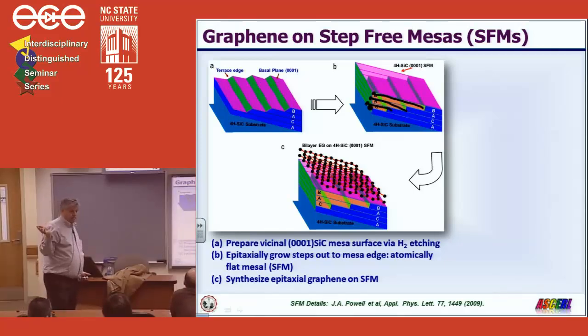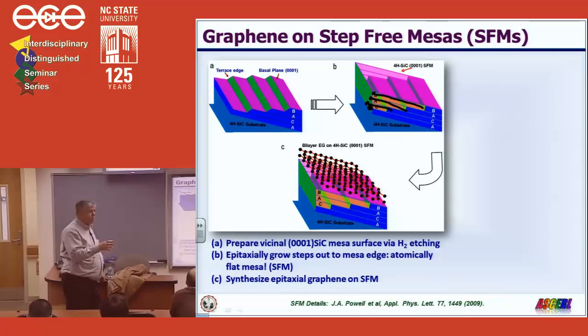I can never grow it out. So you can't just get a 2D nucleation process on the top layer of that mesa? I can. What we did, we grew these mesas specifically to grow 3C silicon carbide on top. And that's a cubic material, and I could nucleate it anywhere on that mesa, and I could grow pretty good single crystal 3C on the mesa. But there's no steps there to grow a hexagonal form of silicon carbide.